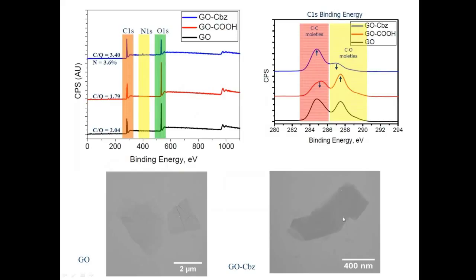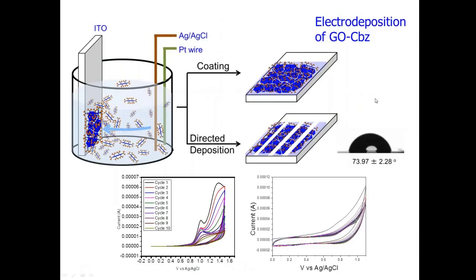Here are TEM images of the graphene oxide and the graphene oxide modified by Carbazole. You can see these are true exfoliated nanosheets that can be derivatized with an organic moiety along the surface. In fact, we can electrodeposit this on pattern arrays and modify the wetting behavior of, let's say, an ITO substrate, as shown in this contact angle.